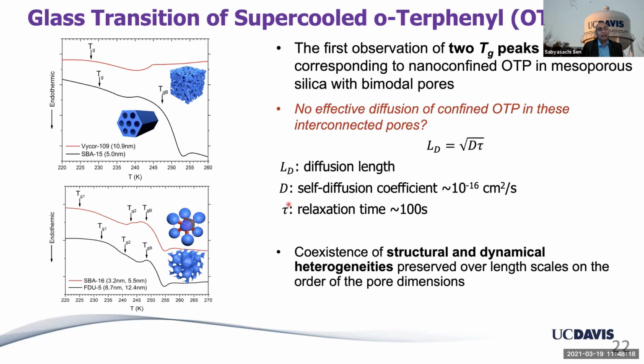For glass or for supercooled liquids, it's easy to calculate that time scale, or the diffusion length associated with that time scale, because we know we are close to TG. So the relaxation time is on the order of about 100 seconds. The diffusion coefficient for molecules in OTP has been studied. The self-diffusion coefficient turns out to be around 10 to the minus 16 centimeters squared per second. So from this back of the envelope calculation, the diffusion length turns out to be about a nanometer.